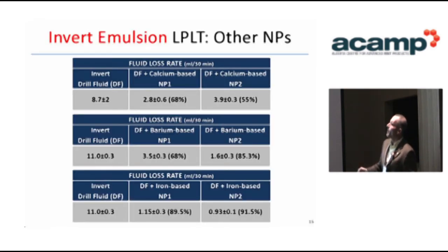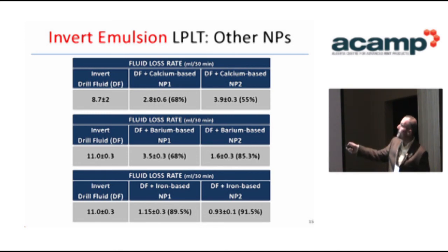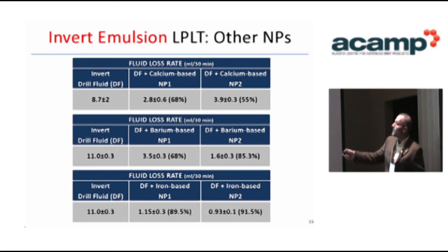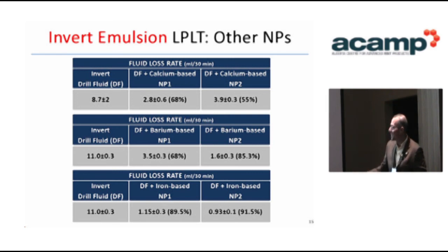We tested other nanoparticle types as well. With iron-based nanoparticles we had already shown results. We then tested calcium-based particles, which are widely used for shales and carbonate formations, and achieved 68% and 55% reduction at low concentrations. Barium-based nanoparticles — barium-based additives are typical for drilling fluids — were also tested. Finally, a different kind of iron-based nanoparticle also typical for drilling fluids showed even higher loss prevention.